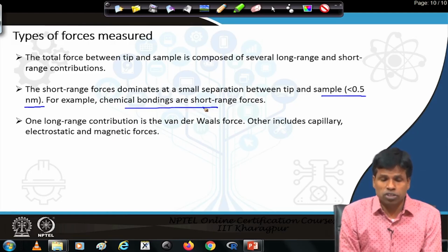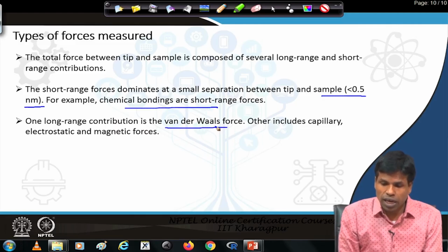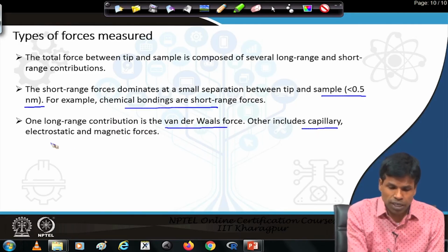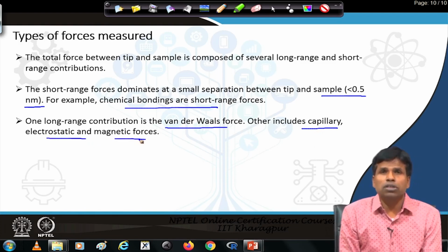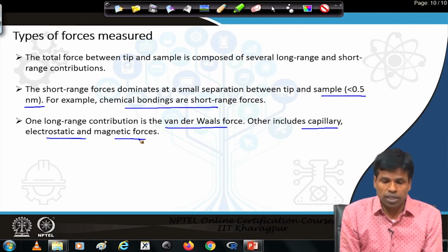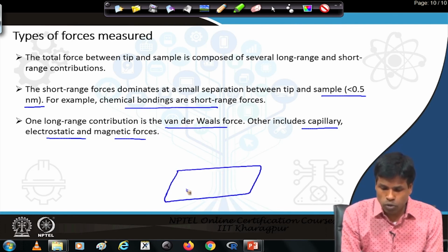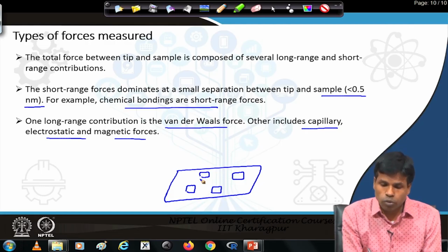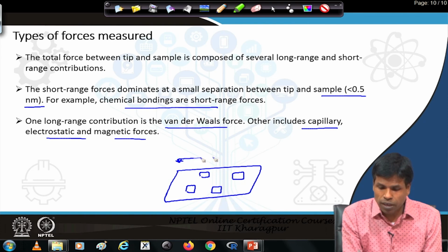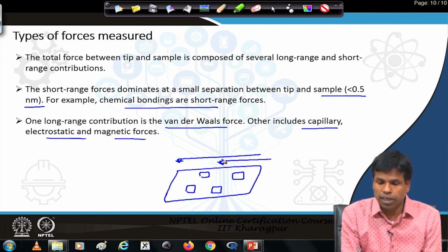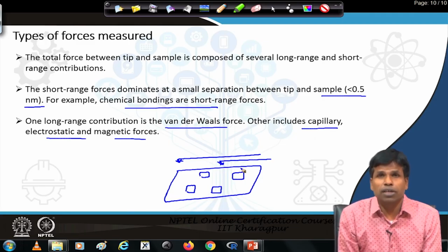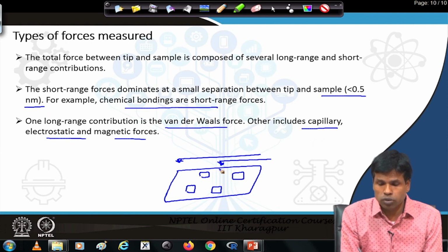And we can also have long range forces like van der Waals forces, and long range forces include capillary, electrostatic and magnetic force, and these types of force can also be measured using atomic force microscopy to study the respective properties. For example, in one sample there are a few regions where magnetic particles are there, and in other regions no magnetic particles are there. Then if our tip or probe goes above the sample, it will detect, and certainly the tip has to be also magnetic in nature, then only the magnetic force can be measured between the tip and sample.